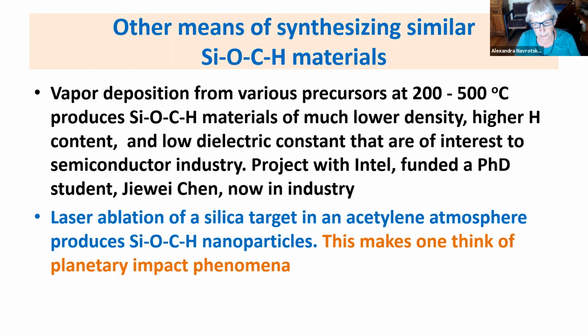Laser ablation of a silica target. Take some silica glass, make a flat target out of it, put it in a vacuum chamber or a chamber that has some sort of gas, have a collection plate on the other side of the chamber, and then ablate the sample with a laser while it's in contact with an atmosphere that contains carbon. Our initial experiments used acetylene gas. Collect the stuff you get on the other side, and lo and behold, it's nanoparticles of something like a ceramic material, like a polymer-derived ceramic, except the particles are smaller and it probably contains a bit more hydrogen.